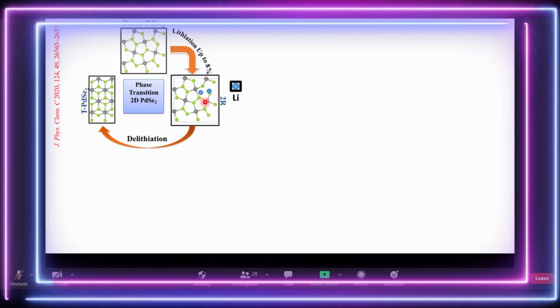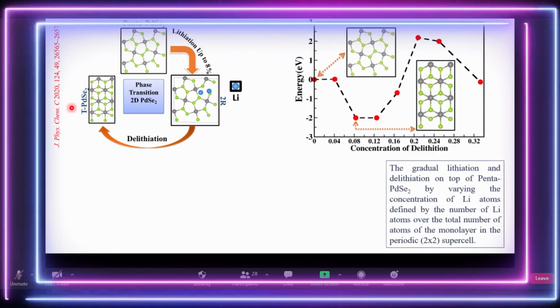You add it, and now you can see the lattice is going to distort, and then what you do is take out the lithium atoms. So you retain what is called TPDSe2, which is a hexagonal structure. And this is a barrier process because we are adding and removing. So if I take the energy versus the lithium atoms and plot it, you can see the energy becomes a minimum and then rises. So this 8% kicks in nicely in expanding the lattice or making a phase transition.